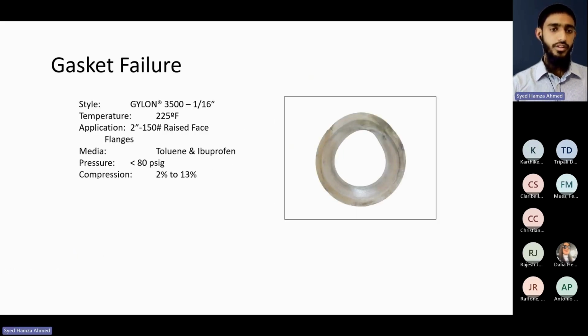Another example here is from Gylon 3500. It was a 1/16 of an inch thickness gasket that was utilized in a 2-inch 150 pressure class raised face flange. Here everything worked perfectly fine. The temperatures were fine for the gasket. The media was perfectly compatible. The chemical compatibility was fine here, and the pressures were not too high. They were also within the range.